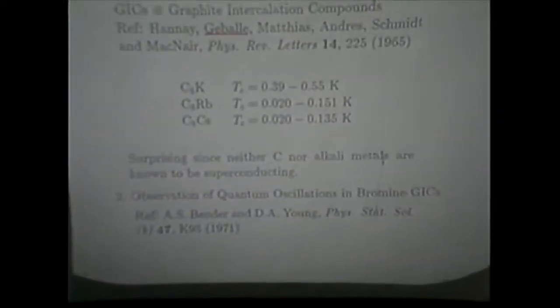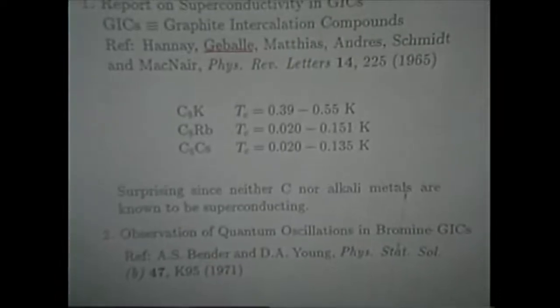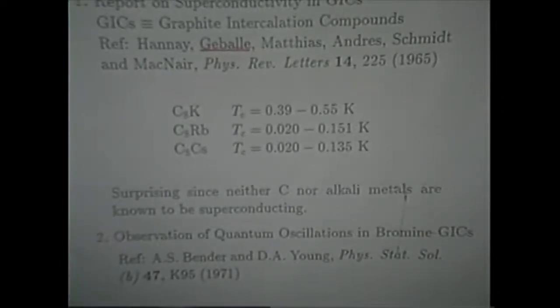We take carbon in the form of graphite, and we add to the carbon alkali metals, potassium, rubidium, and cesium, and lo and behold, we get something that's superconducting, when we know darn well that none of the constituents that we put in there are superconducting by themselves. This is a very interesting phenomenon. Perhaps you could do some of these high-field magnetoreflection experiments and learn something about what happens to the modification of the band structure of graphite that promotes superconductivity.